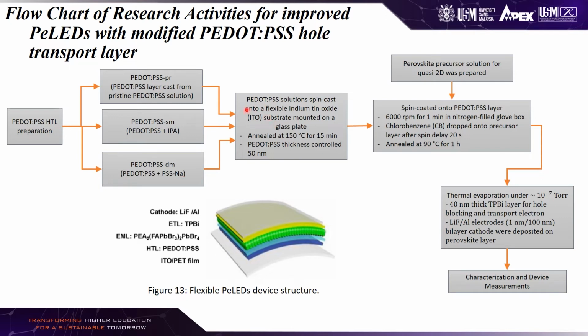The PEDOT:PSS solution is spin cast onto a flexible indium tin oxide (ITO) substrate mounted on a glass plate and annealed at 150 degrees Celsius for 15 minutes. The PEDOT:PSS control has a thickness of 50 nanometers.